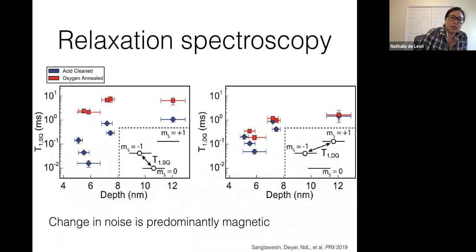We can also do a different type of spectroscopy of the bath by taking advantage of the fact that the NV center is a spin 1 system and looking at spin lattice relaxation. Specifically, we can look at spin lattice relaxation between the ms = -1 and 0 states, which is a single quantum transition. And then we can also look at relaxation between ms = -1 and ms = +1, which is a so-called double quantum transition. This is a little bit of an oversimplification, but in general, magnetic noise can drive these single quantum transitions, but not the double quantum transition. So this double quantum T1 is more sensitive to electric field noise. And what we see is that between these two surfaces, there is a very large change in the single quantum T1 and a very small change in the double quantum T1, which indicates that this change in noise is predominantly magnetic.